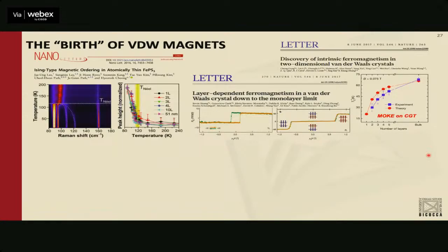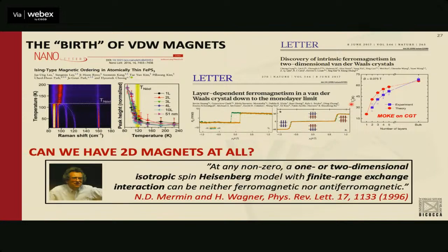So, as I told you, this 2D boom started with graphene. But then in 2016 or 17, people discovered that even a monolayer or a few layers of some magnetic crystal would order. The paradigmatic cases are chromium-I3 and chromium-germanium telluride. And people discovered that there is a certain ordering that emerges below a certain temperature. And so there was a question, right?